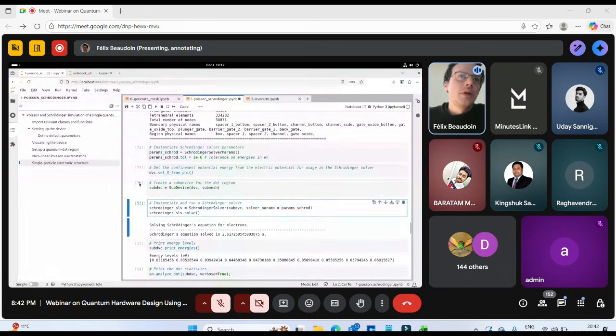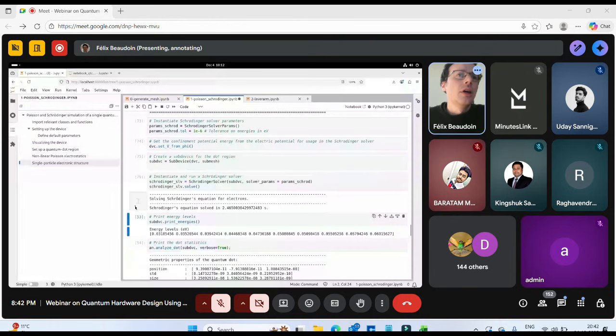Because I'm running on multiple cores right now, in only 2 seconds, I got the results. On my laptop, it's something like 30 seconds. We can print the energy levels of the quantum dot, and we can also use this analyze dot method to print geometric properties of the quantum dot, namely its position, standard deviation of the ground state, and size of the quantum dot in SI units. So here we have a quantum dot that is 32 nanometers by 15 nanometers by 3 nanometers, roughly.